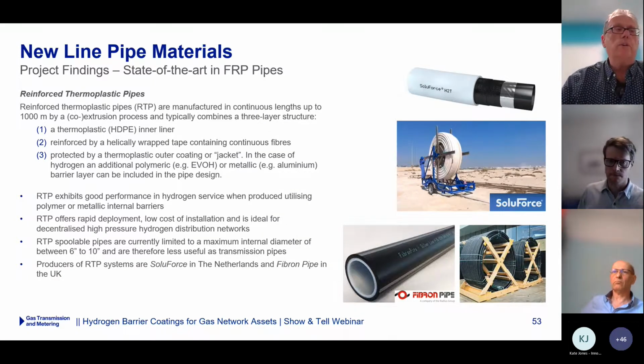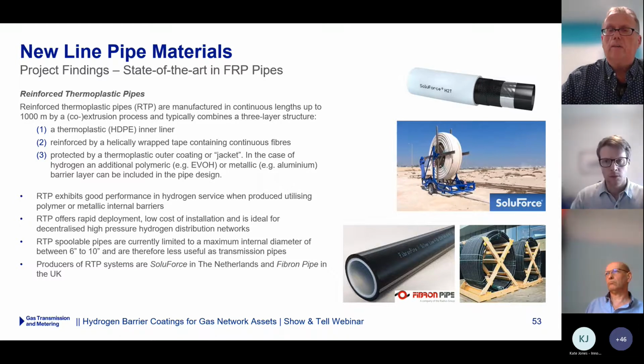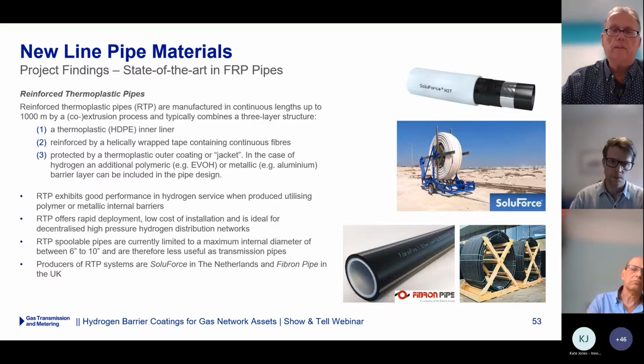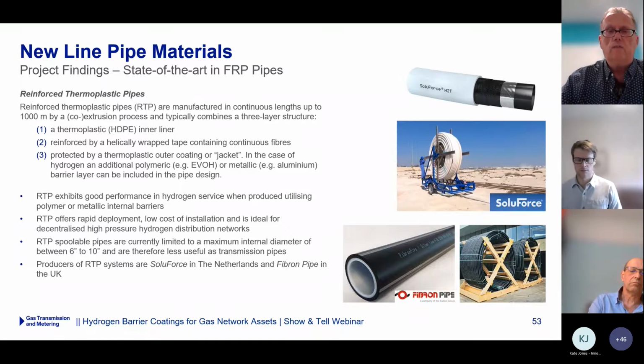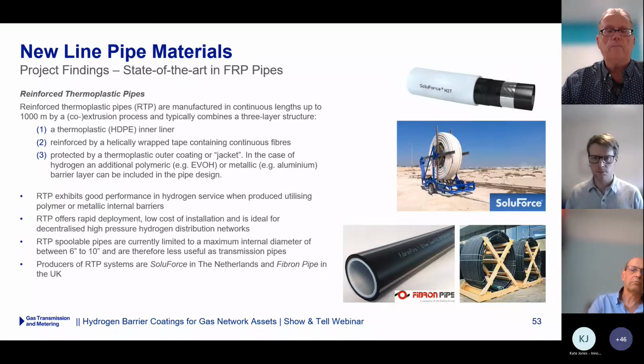So, for example, you could extrude a pipe by co-extrusion, that means extruding 2 polymers at the same time, where a polymeric layer based on ethylene vinyl alcohol, which has very good barrier properties, very low permeability, can be included directly in the process. But as I said, the technology that is out there is mostly limited to smaller diameters, which maybe rules out this technology for transmission pipes. Next slide, please.